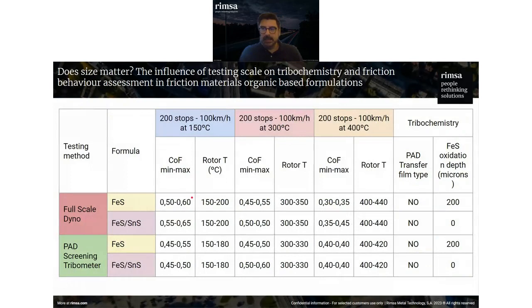And we may say, as a summary of these results, that with the full scale dyno, neither in the iron sulfide formula nor in the iron sulfide tin sulfide formula do we have any pad transfer film, because these formulas don't generate this transfer film. And after this 400 degrees test, the oxidation depth achieved by the iron sulfide is around 200 microns, both in the full scale dyno and the pad screening tribometer, and we don't have any oxidation of the composite of iron sulfide and tin sulfide, neither on the full scale dyno nor the tribometer.